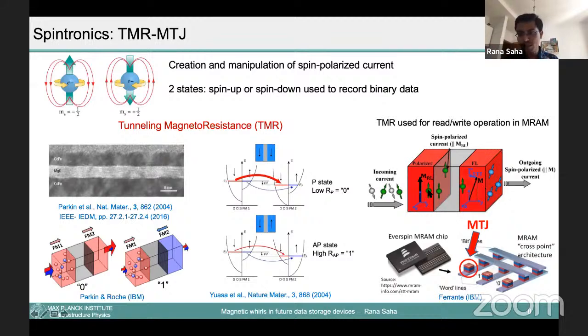So what happens when this spin crosses the first layer? It takes the up spin because it is fixed, and when it enters this layer, this spin transfers its angular momentum to the spin on the right side, and because of that it feels a torque, and in this way the spin can switch. So it can switch from parallel to anti-parallel or anti-parallel to parallel. That's how, by passing current, you can write 0 and 1 bits. Also, you can read by passing a small current whether it is in the 0 or 1 state.